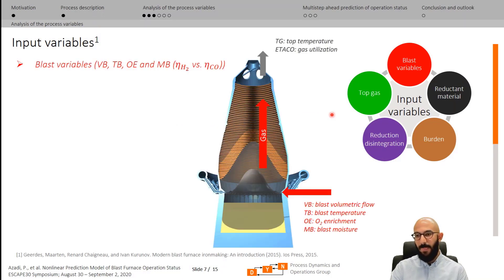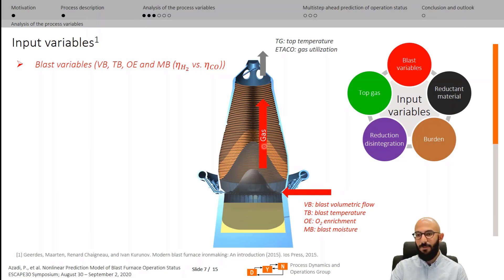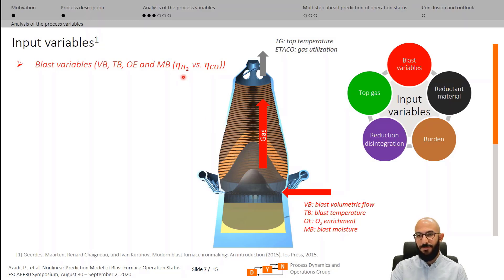Input variables predicting the gas analysis can be categorized into five major groups. Starting with the blast variables: hot blast is the origin of the gas, and due to the very short residence time of 6 to 10 seconds, any changes in hot blast variables can directly be identified through the top gas analysis. Increasing the blast volume, temperature, and oxygen enrichment results in more gasification in front of the tuyeres, more gas production, and higher intensity of chemical reactions, identifiable through top temperature and gas utilization factor. The moisture content of the hot blast is responsible for hydrogen production; therefore, manipulating this variable controls the portion of reduction reactions by hydrogen and carbon monoxide, identifiable in eta-CO.